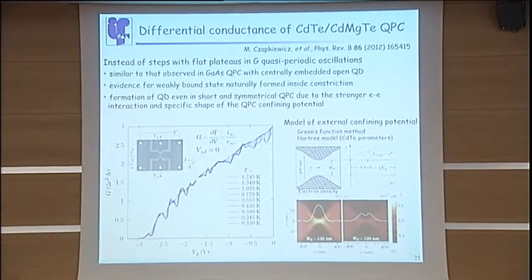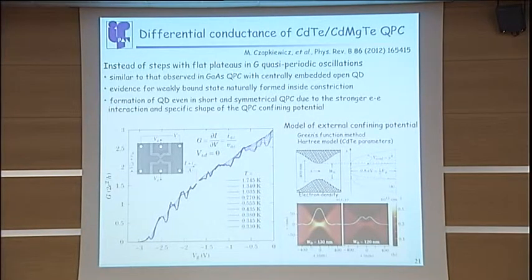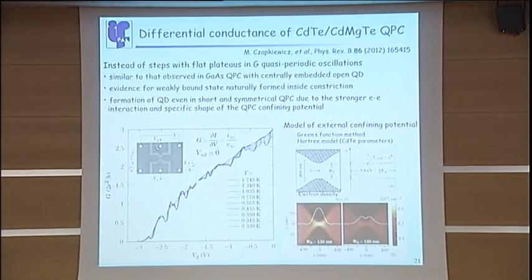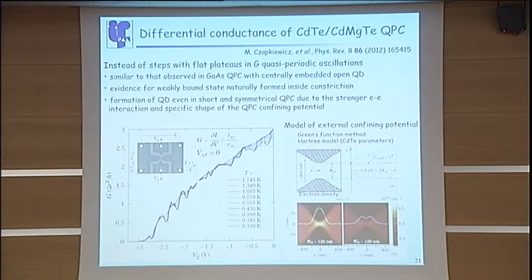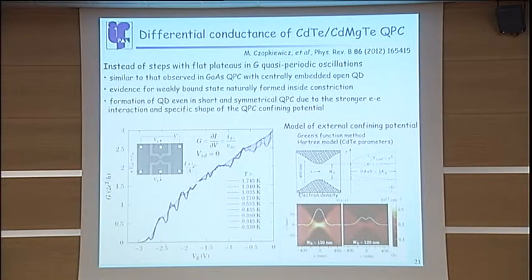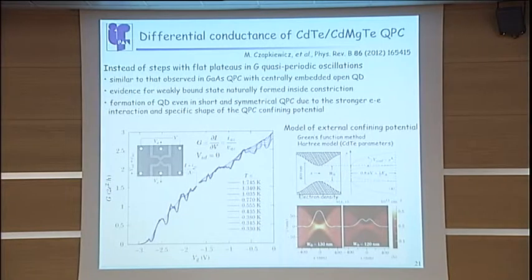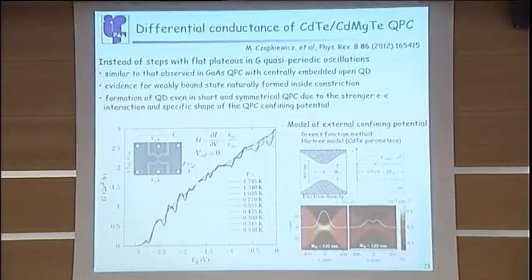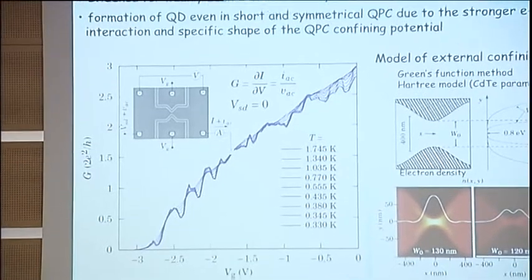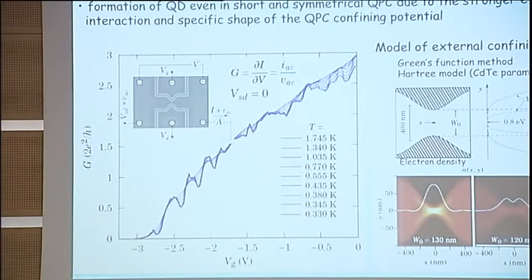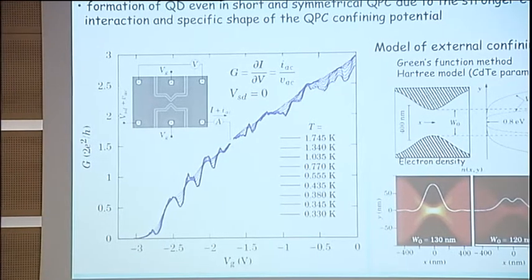And having already reasonable quality quantum structures, we have started to make lower dimensional structures, and the first and simplest one is of course the quantum point contact, and there was also a nice poster at this conference about this. I only want to mention that we succeeded in producing a quantum point contact by wet etching and e-beam lithography, but instead of flat plateaus in conductance, we have observed quasi-periodic oscillations. Due to the similarity of this observation to a similar observation in gallium arsenide, in which a quantum point contact had intentionally produced a quantum dot, we interpreted our data as those oscillations being due to natural formation or self-formation of a quantum dot, due to the stronger electron-electron interaction and specific shape of the confining potential.